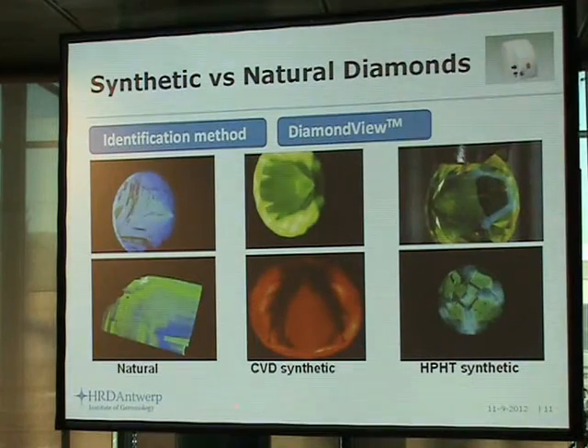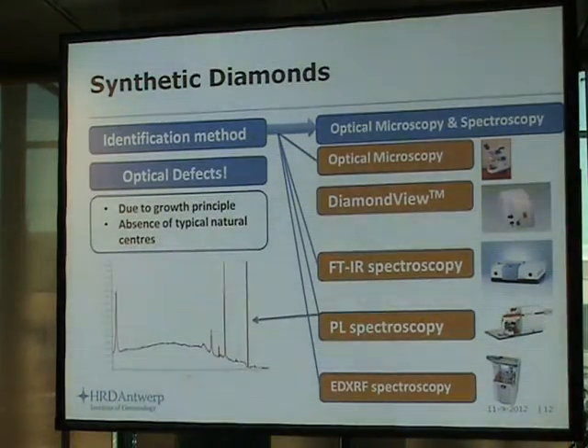For the CVD, it's a bit different. There you have that plasma growth. It's layer by layer. And if you look closely here, you see that quite regular structure, or layered structure again. And that's for us, or for you, a clear indication, not a decision, for CVD synthetic diamond. Of course, that's our indications. What we do within research at HRD Antwerp for issuing certificates is use a combination of more advanced techniques, going from optical microscopy to other spectroscopy techniques, to investigate, in fact, typical defects in the diamond, because they are the key to identifying the synthetic origin of these diamonds.